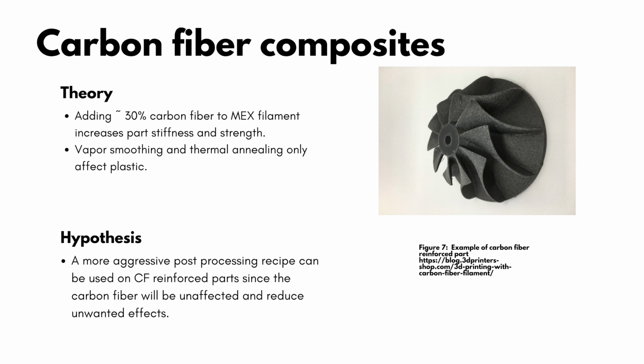The idea behind this is that we can use a more aggressive post-processing recipe on carbon fiber reinforced parts, since the carbon fiber will resist the unwanted effects. The fibers will reinforce sharp edges through a vapor smoothing process and prevent shifting and warping during thermal annealing.